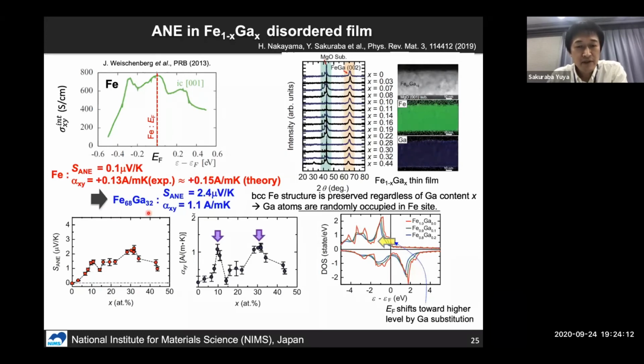And after measuring other parameters systematically, we observed very interesting behavior in alpha XY. As you can see, in the gallium composition dependence, alpha XY showed a very strange two-peak structure like this. So why did these two peaks appear? We performed a first-principles calculation of the density of states for BCC randomly disordered iron gallium. As a result, we found that by adding the gallium, the Fermi level slightly shifts by the charge transfer from the gallium sp density of states to the d states of iron.